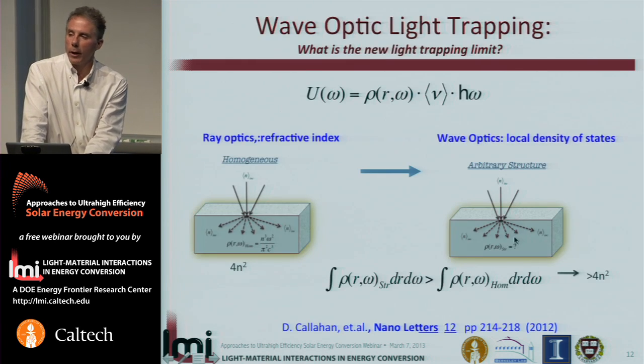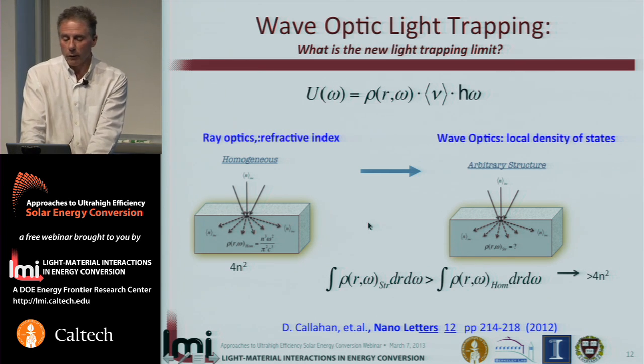And if we think then about the current technology that focuses on thin film cells, where the entire cell thickness is of the order of a wavelength thick, then we can no longer use ray optic models to describe the picture, and we need to adapt this statistical ray optics picture to a wave optics picture that takes into account the coherent excitation of modes in cells where the entire thickness is comparable to the wavelength. The appropriate description of the internal energy density is then in terms of the mode density times the energy per photon excited in the mode times the modal occupancy. That leads naturally to the notion that this local density of optical states, often termed local density of photonic modes, is a key quantity in determining what the internal intensity, and therefore the absorption, in such a wave optic, wavelength-scale thickness solar cell could be.